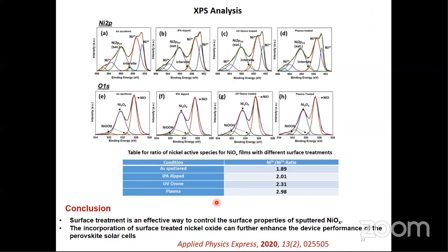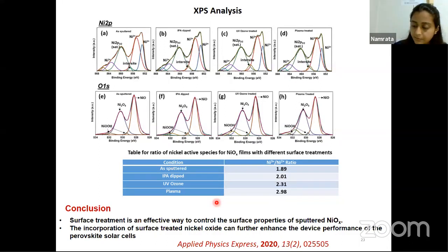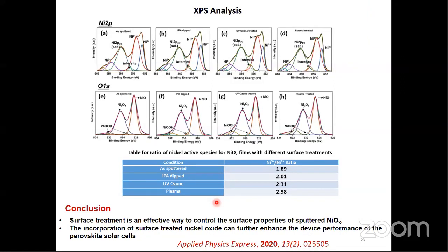One more question. Can you tell us the thickness of the nickel oxide film? In case the thickness is less than 20 nanometer, how is it possible to get XPS data like that, he asked? Yeah, it's a nice question. We optimized the thickness, and the best efficiency was obtained with 40 to 50 nanometer of nickel oxide. I can understand that with 20 nanometer it's not possible.